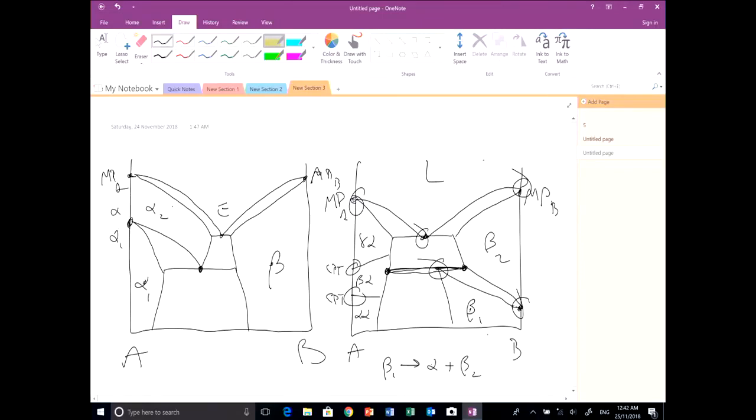Isn't that alpha 1 goes to alpha 2? Yeah? And that means as we dissolve B into it, the transformation temperature drops, doesn't it? Okay? Suppose that phase transformation is very bad for us. It causes structural destabilization, and we don't want it. So that tells me that any impurities of B, when I process A, are really critical because they're going to drop my transformation temperature. So I've got to be very careful to exclude B from my impurities.